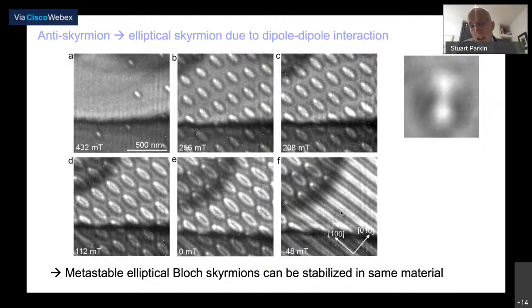And without going into any details, it turns out that the reason for the formation of these elliptical Bloch skyrmions and the reason for the variation in size of the antiskyrmions and the helix period with thickness is derived from long-range dipole coupling. And it's a property of the very low symmetry of the crystal structure of these Heusler compounds as compared to the cubic B20 materials that have been so heavily explored. So this is a very interesting and unusual property of the Heusler compounds.